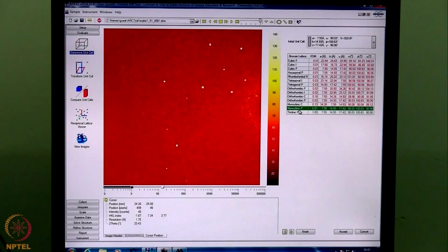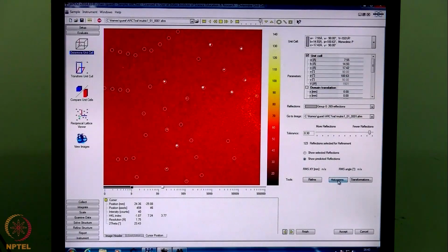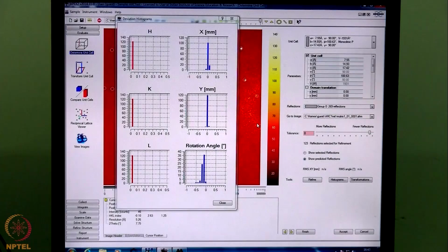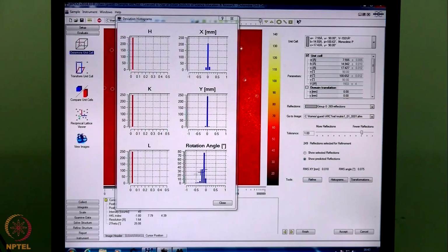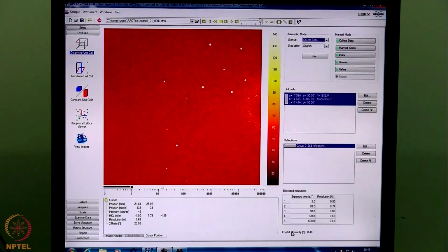Now when we try to determine the Bravais lattice, it finds that it is a monoclinic lattice with 90.03 and 90.06 as alpha and gamma, with a high figure of merit of 0.81. So we choose that monoclinic lattice, go forward and do the refinement once again with tolerance 1. Still we see that this rotation angle is slightly on the left, which indicates that the crystal is not properly centered. So now what we have got is a monoclinic lattice with a volume of 1933 cubic angstrom.